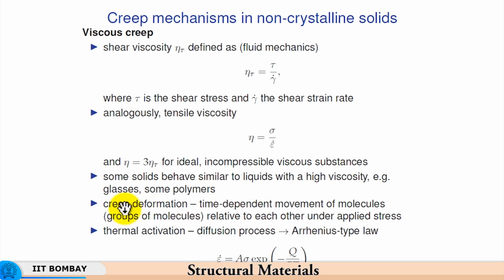So, you have some solids which behave similar to liquids with a high viscosity, like non-metallic materials such as glasses and polymers, because the whole mechanism of deformation is different. Glass is a supercooled liquid and it is amorphous in nature, and therefore you will have viscous effects, which will be the only ones that play a role in deformation of the glass or creep of these glasses at high temperatures.